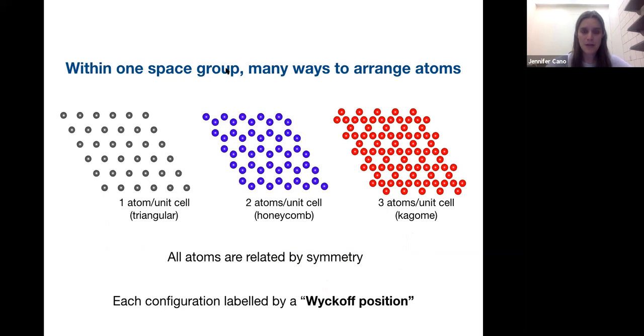So for example, if we have the symmetry group consisting of a six-fold rotation and mirrors and translation symmetry, we can get a triangular lattice. But we can also get a honeycomb lattice, and we can also get a Kagome lattice. The difference between these lattices is the number of atoms per unit cell. But also there's a more important difference, which is that you can think of each one of these lattices as having a different group of symmetries that leave one atom invariant. So for example, if we look at the triangular lattice, and if we do a six-fold rotation or a mirror reflection, each atom is invariant under all those operations. So that's why there's only one atom in the unit cell.